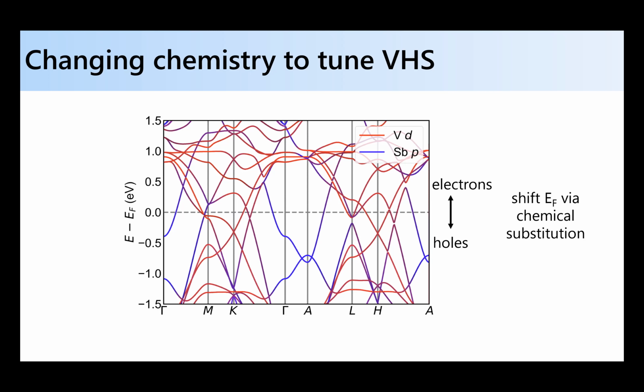Okay. So there's a lot of materials talk, so I get to talk about what we do with brute force, because I can't do these STM measurements that Vidya does, but we can definitely tune the filling by doping electrons or holes in the system, and then we can ask what happens to the charge correlations, to the instabilities of the system as we tune the Fermi level about these supposedly important features coming from the kagome net.